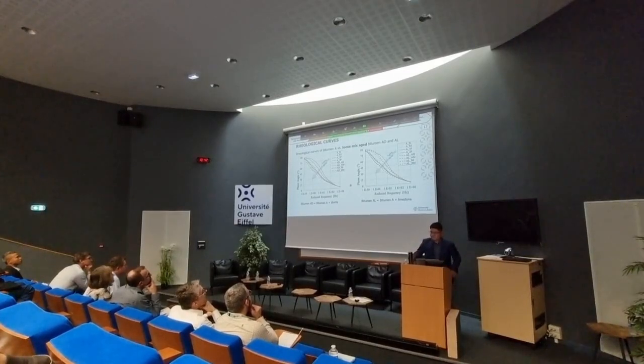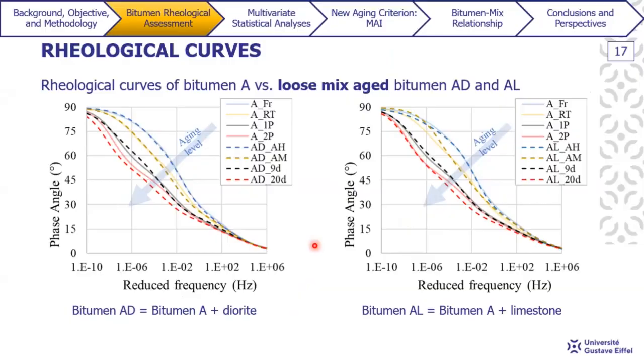This one, yes. So from this slide, you can say that the phase angle decreased due to aging. But I don't completely agree with this simple conclusion. If you look at the reduced frequency, obviously it decreased. But what is interesting for this material is the frequency of loading, the mechanical solicitations, but also temperature. With this graph, you can conclude if, for one temperature, the phase angle will decrease or increase.